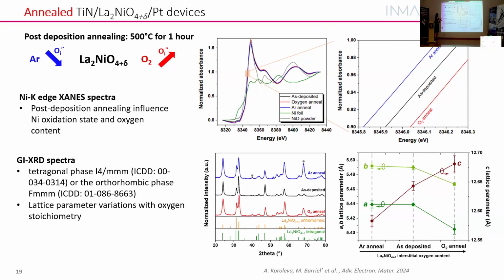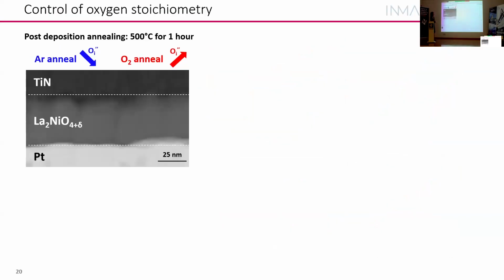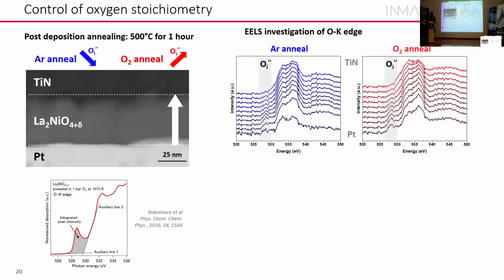Then we deposit... We see the same by XRD. So when you introduce oxygen, the C parameter expands and the AB plane decreases, exactly as we expected. So then we checked by EELS what is happening exactly below. Well, okay, these are annealed samples. We put the titanium nitride on top. And as I said before, this titanium nitride tends to oxidize the sample.